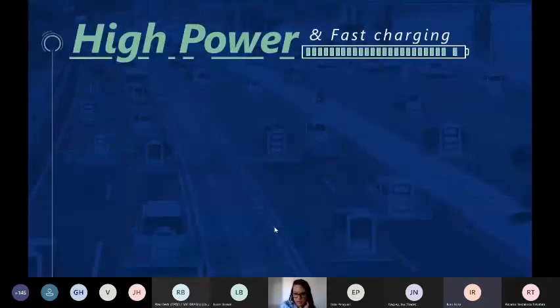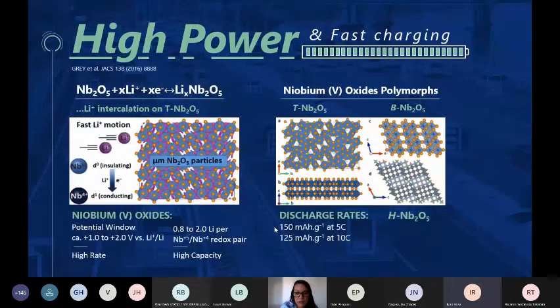Talking about anodes or negative electrodes. New niobium-based materials have been developed as battery anodes because they improve the mobility of the lithium in the structure by creating spaces, resulting in high charge and discharge rate properties and high power. In contrast to conventional materials such as graphite, which under conditions of fast charging can undergo lithium plating, which can cause a short circuit in the system, for example. This affects not only the stability of the material, but the safety of the battery.